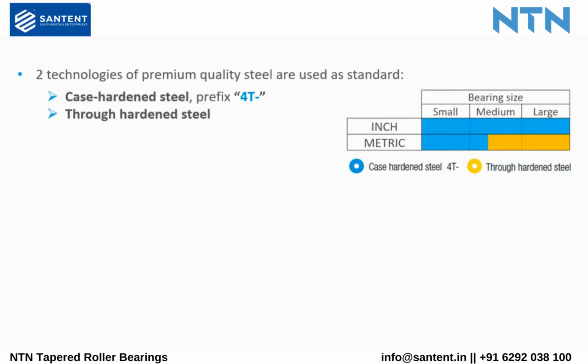NTN tapered roller bearings use 2 steel technologies as standard. Case hardened steel, which is treated to obtain a surface hardening and allows the core to remain softer and therefore more resilient, is applied to the rollers and both rings and is identified by the prefix 4T. The entire inch range is case hardened, as is approximately 35% of the metric range for the smaller ones. The rest of the metric range is made of through hardened steel.